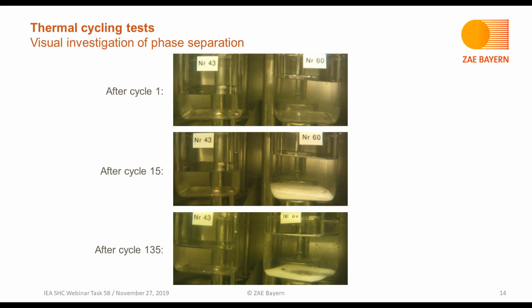And then continuing the cycling after cycle 135, there's still some solid material on the right sample at the bottom, but what is also visible is that the amount has slightly decreased. So there seems to be a kind of stabilization process.